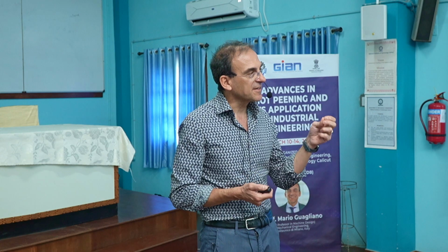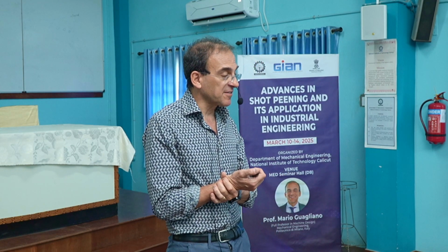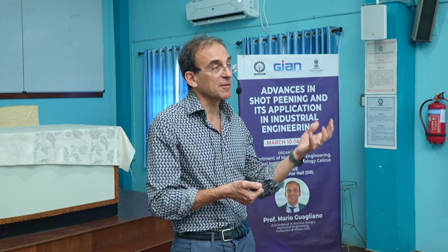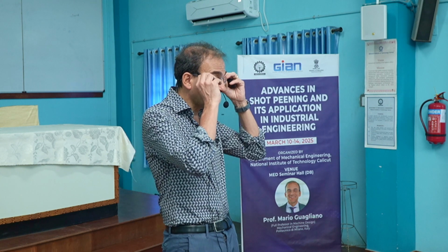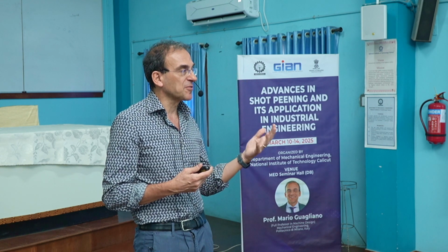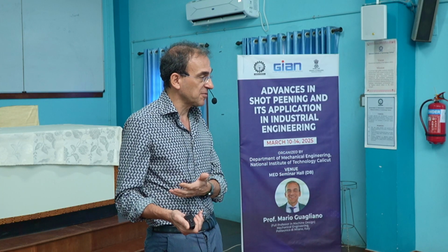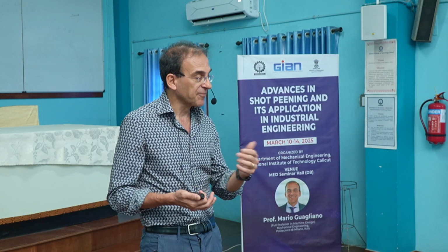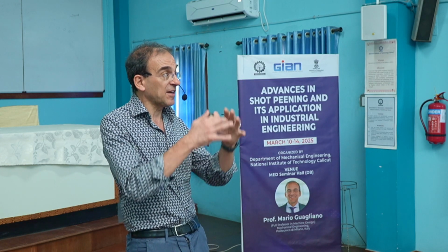As I said, it was developed by David Taylor at Trinity College in Dublin, Ireland. Taylor started from the fact that fatigue damage does not affect just the surface, but a very small layer of material that varies with the stress gradient. Indeed, the maximum stress at the notch root is not the most appropriate choice of damage parameter. That is not different from considering that the stress concentration factor for fatigue is different from the theoretical stress concentration factor. These are all related, but this is proposing something more analytical than just a coefficient.